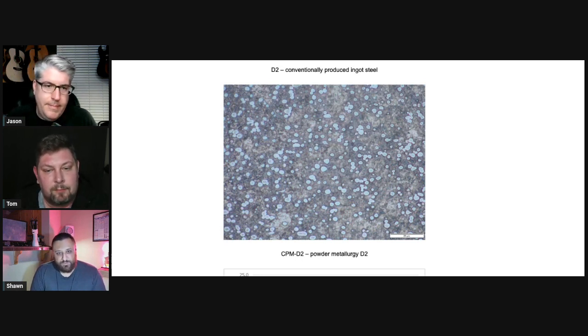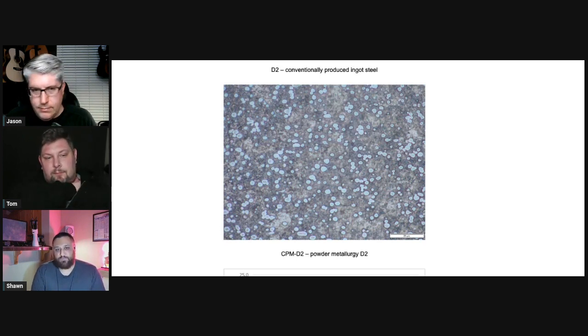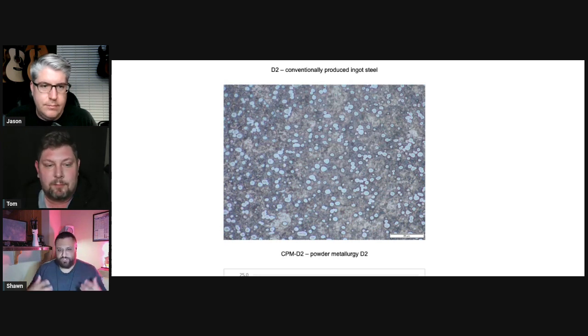So CPM D2 will give you more toughness, but it looked like with the CATRA edge retention testing, it didn't necessarily translate to more edge retention between D2 and CPM D2, because the carbides are still the same hardness. Technically, I believe they're still at the same volume, but it turned out the toughness was increased because it's more homogeneous. We have less non-uniformity throughout the matrix, where you have areas of just hard carbide, then matrix, and then hard carbide. It's more evenly dispersed throughout.